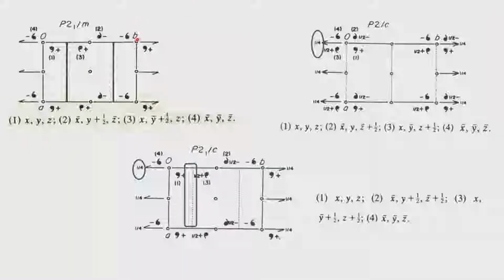In other words, if it is a two-fold axis operation or a mirror alone or a combination of 2 and M, whether it is a 2-1 by C operation, all these symmetry operations are restricted to operate only along the y direction, and that is why it is called a unique axis in a monoclinic system, and that B axis therefore is the one which shows the presence of the two-fold along with it.